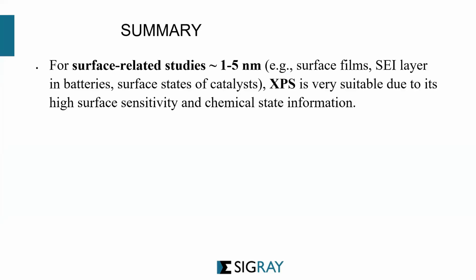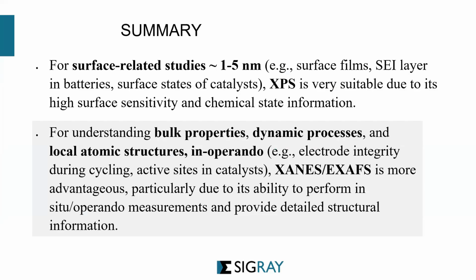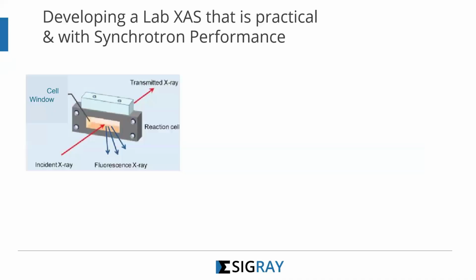So in summary, if you're looking for surface-related studies, XPS is the go-to characterization tool. It's good in batteries for surface films, for SEI layers, and also the surface states of catalysts. But if you are looking for bulk properties or dynamic processes, and the ability to do in operando experiments, there is nothing that can beat XANES and EXAFS because of their diversity and ability to solve this type of problems.